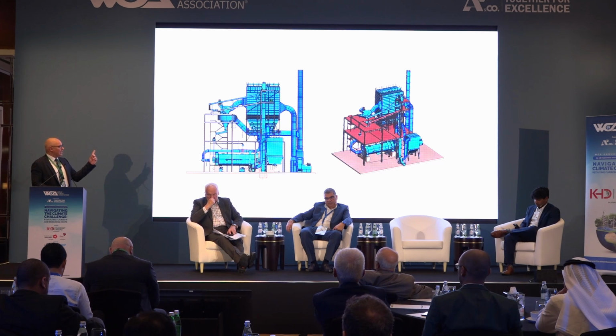What is happening at the end is that I will go directly to the coarse cements. You see, coarse cement, they were producing a GU cement, general use, general purpose. Coarse cement, you see the difference between before and after. I don't know why part of the slides are missing with the headers, but okay. So you can see that the difference between before and after is not a big change. So we are going into coarse cement, 3,000, 3,200 Blaine, not a problem.